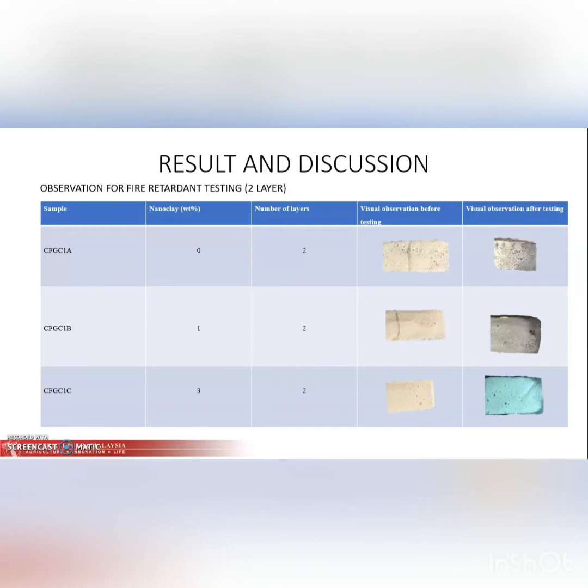After 30 seconds of burn time, the sample with 0% of nanoclay shows a clearer black char effect due to the burning. As the weight percent of nanoclay increases, the char effect shows less color. The addition of nanoclay helps to slow the rate of burning of the carbon fiber geopolymer composite.